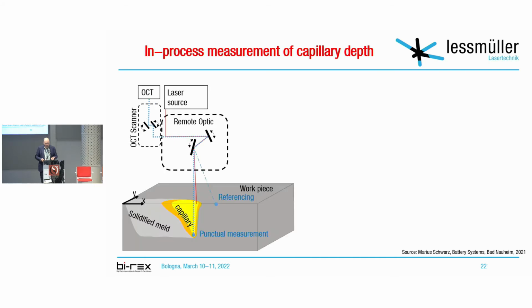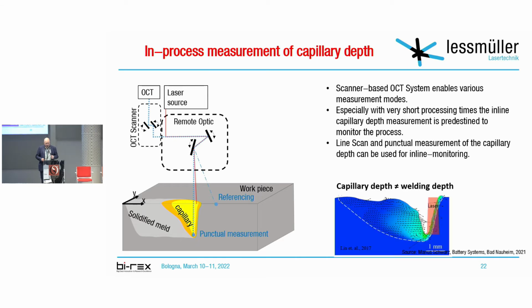And then, during the welding, we look into the keyhole. The keyhole typically has a certain shape, and this shape depends on speed, power, and material. We're not measuring the welding depth, we're measuring the lowest point of the keyhole, which typically is a little bit less than the penetration itself, because you have the heat affected zone. Second, the lowest point is not in the middle of your laser spot, but slightly behind, and that's why with our OCT scanner we can position the measurement point slightly behind the real welding laser.